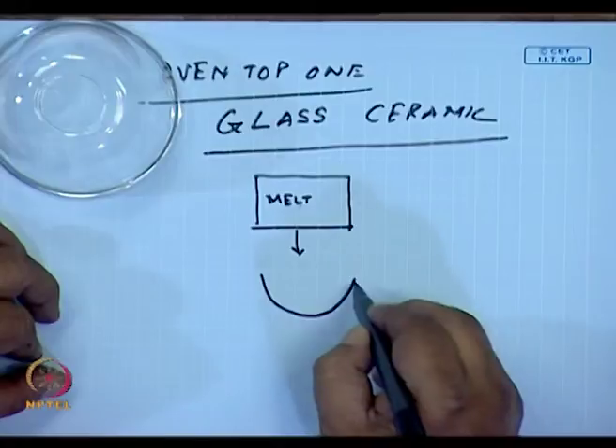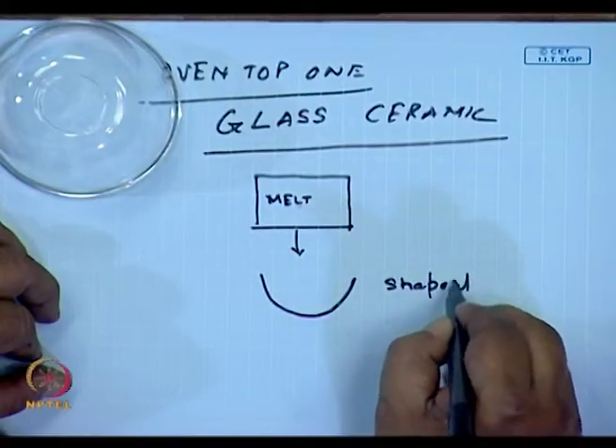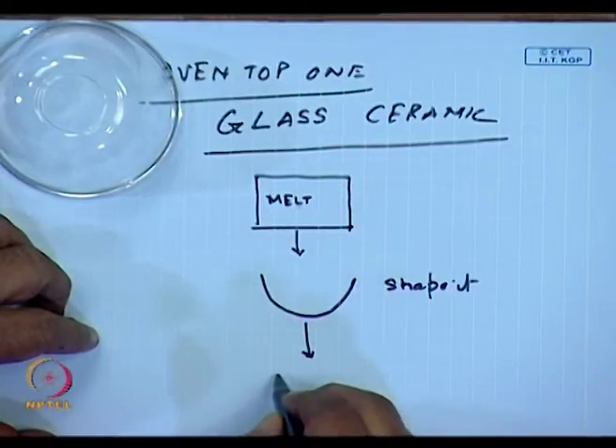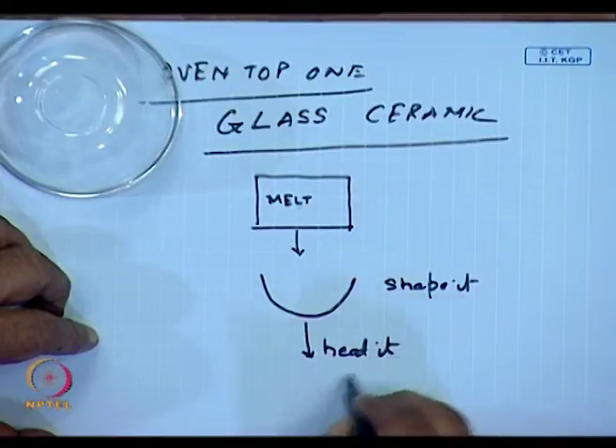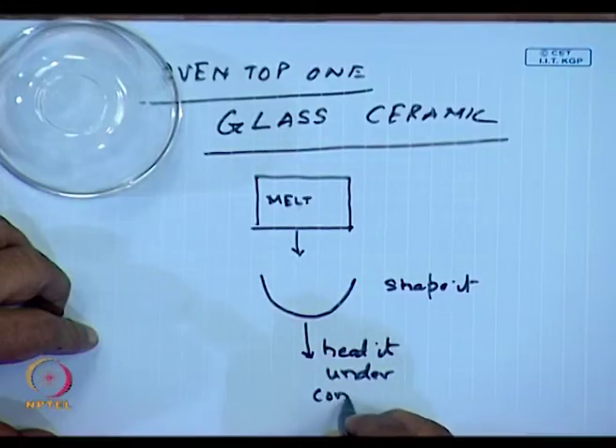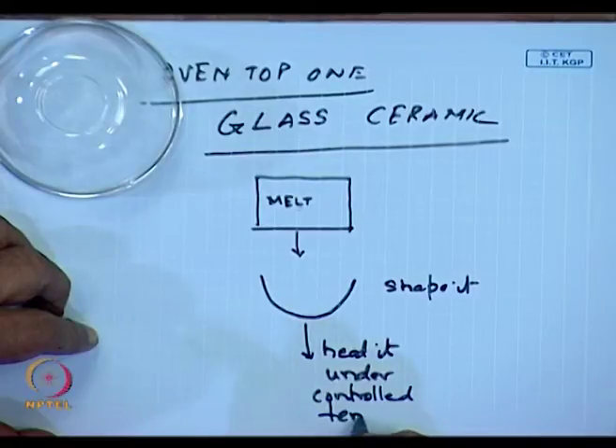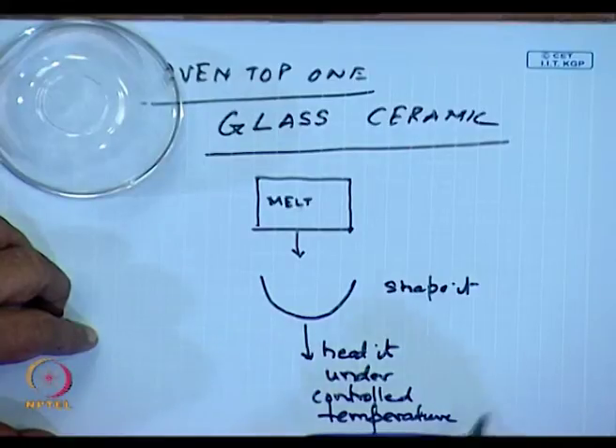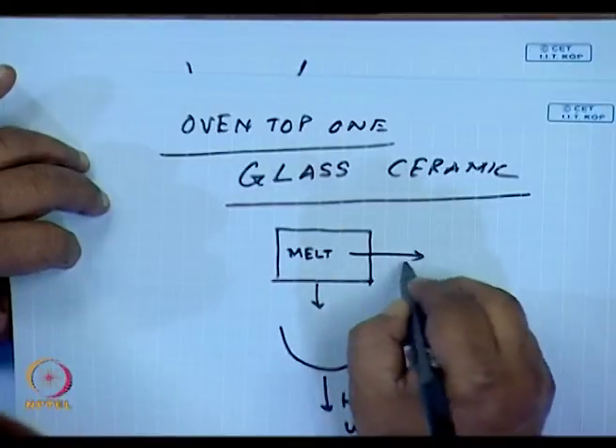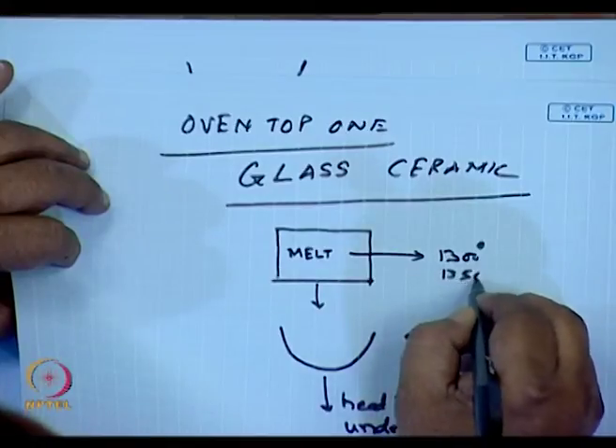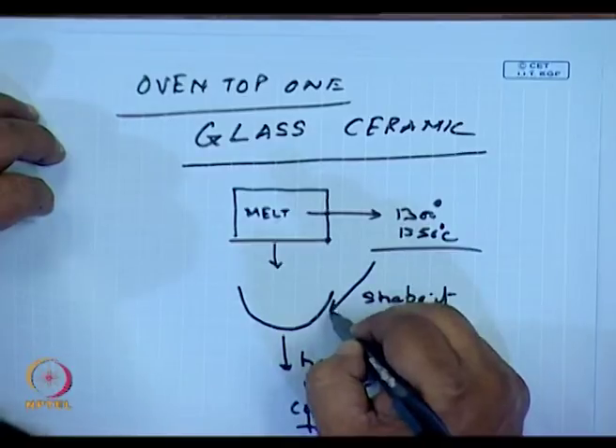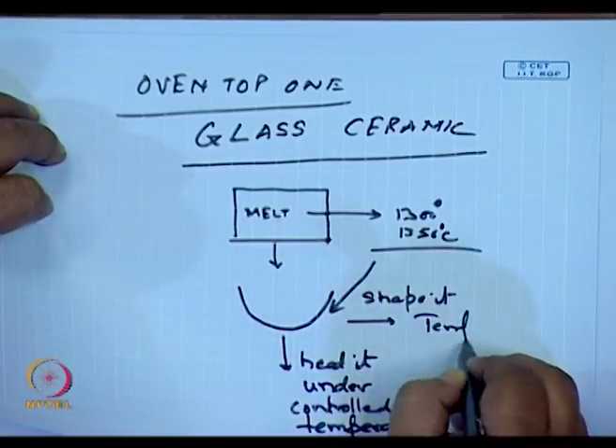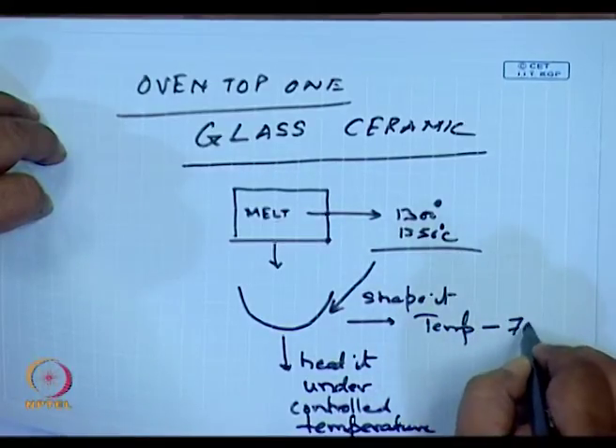shape it, and heat it under controlled temperature. Once it has been shaped, the temperature is obviously nowhere near the melting temperature, because the melting may occur at 1300 or even 1350 degrees centigrade. By the time I have shaped it, the temperature has fallen to 700 degrees centigrade.